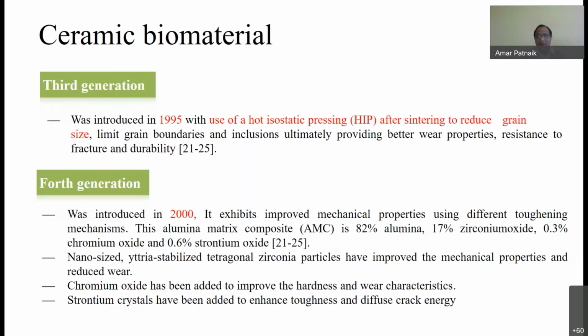Then the fourth generation, what they identified was an alumina matrix composite with 82% alumina, 17% zirconium oxide, 0.3% chromium oxide, and 0.6% strontium oxide. They observed that the properties were slightly better than the first three generations, as the hardness improved and the wear resistance also improved. By using chromium oxide and strontium, there is an enhancement of toughness as well as fracture energy. So that is the fourth generation's identification. It's only these generations.